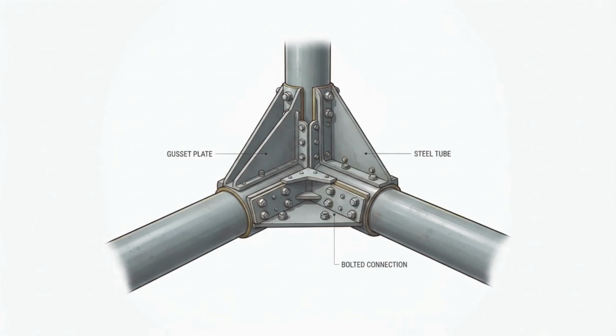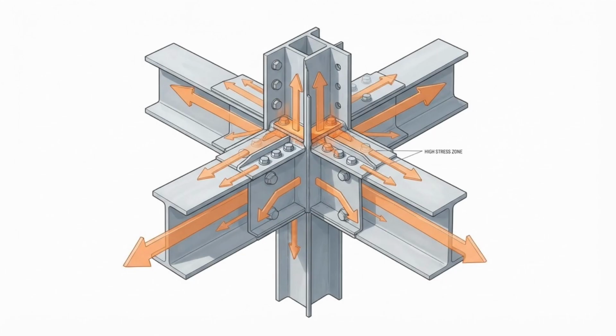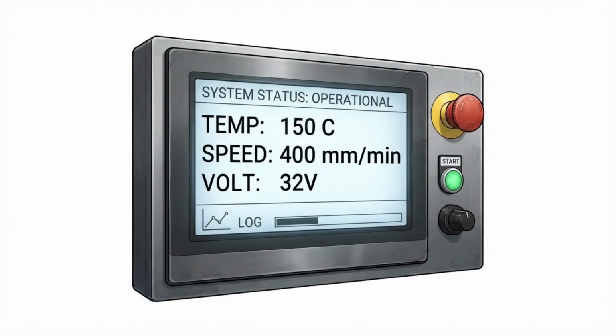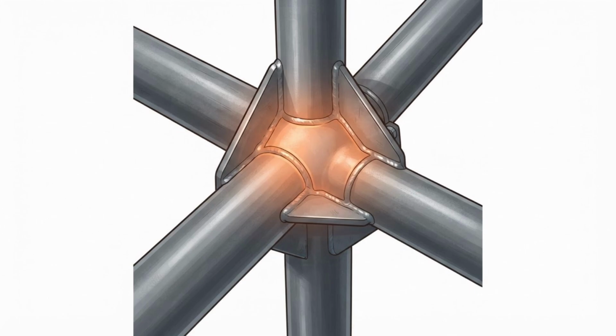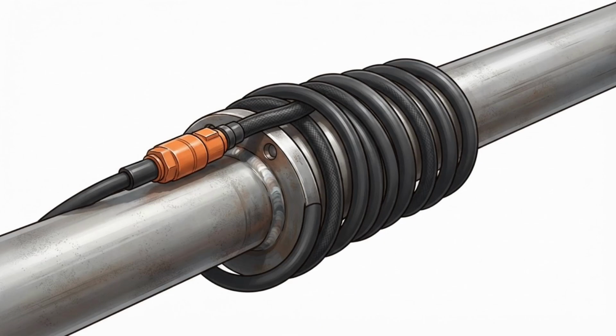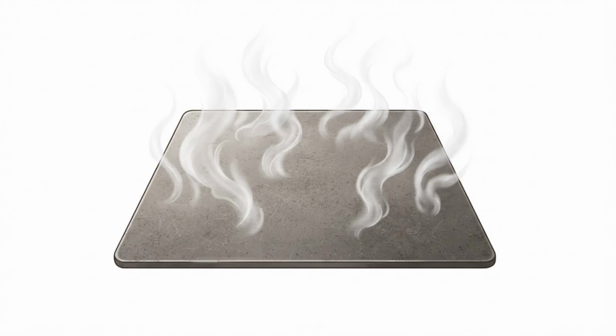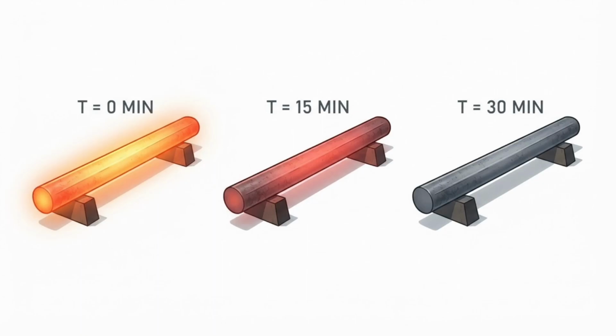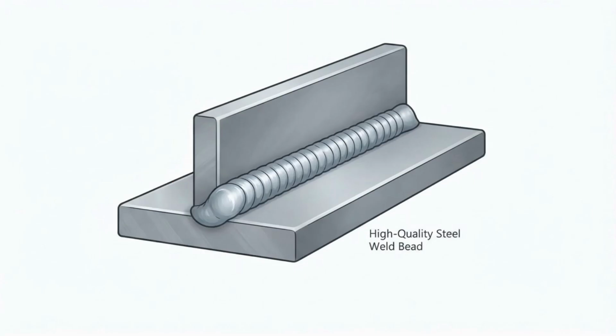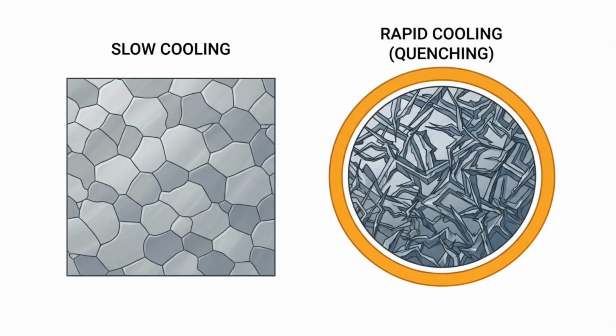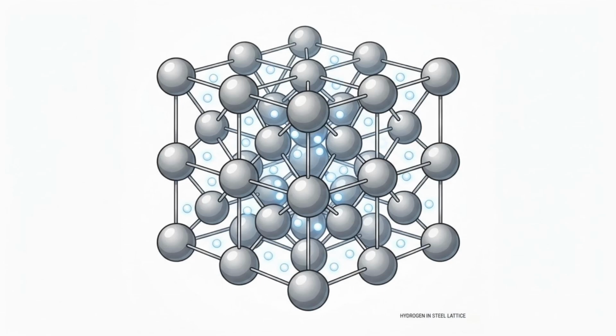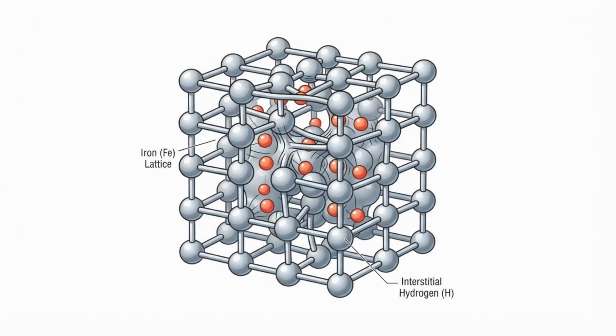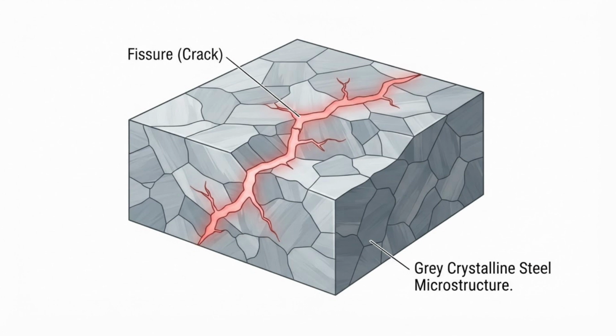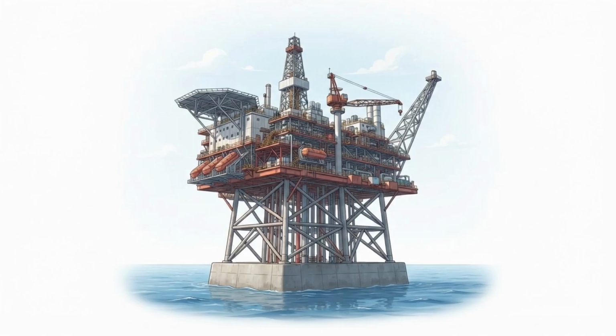Because these nodes will bear the concentrated stress of the entire platform, the welding process is meticulously controlled. The steel around the joint is preheated using heavy-duty induction coils to drive out any trapped moisture and to slow down the cooling rate of the weld. If the steel cools too rapidly, microscopic amounts of hydrogen can become trapped in the crystalline lattice, leading to cold cracking long after the rig has been deployed.